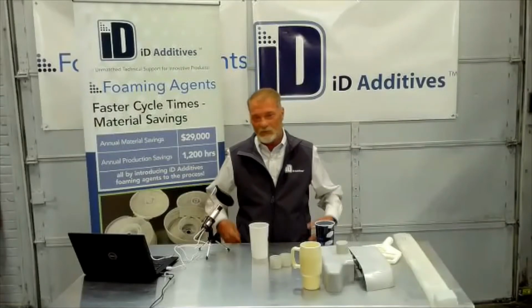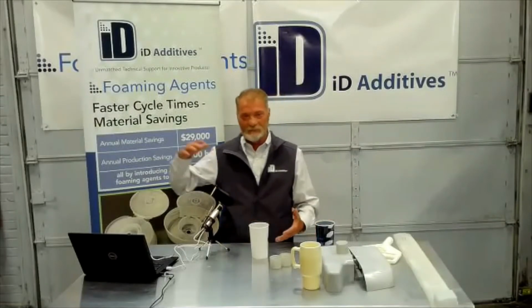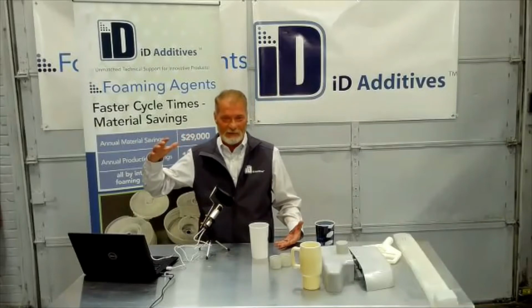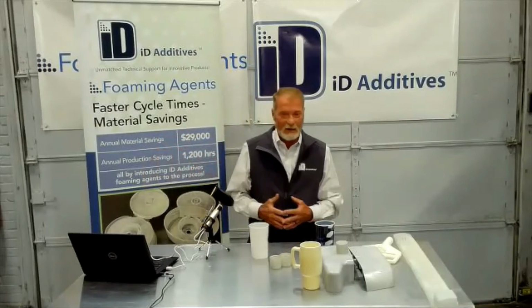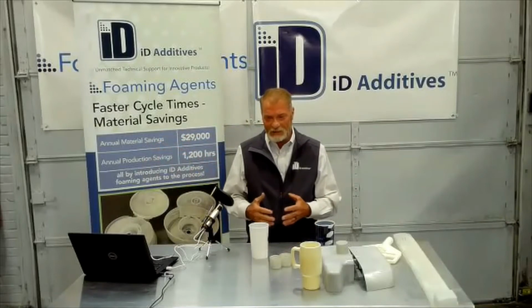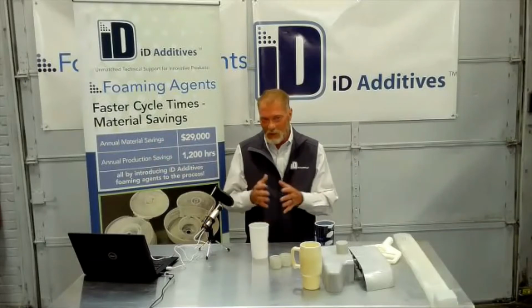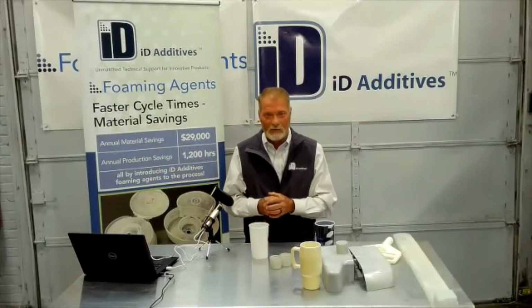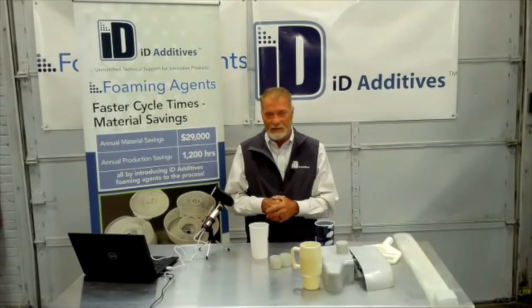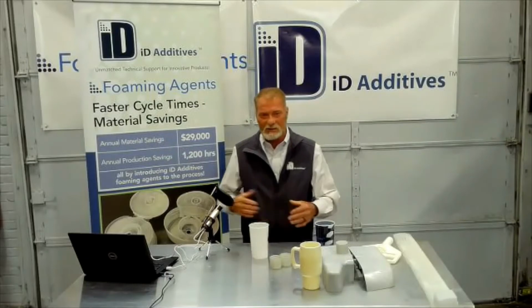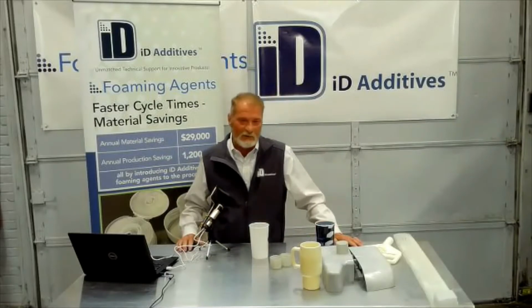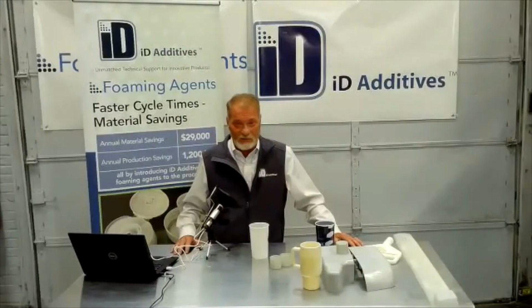If you go 10% calcium, you're going to add weight to the part. The calcium creates nucleating sites for the foam. The bubbles are extremely small, and they just perform really well. And you can still lower temperatures with high loads of calcium and still get a good flow with foam.